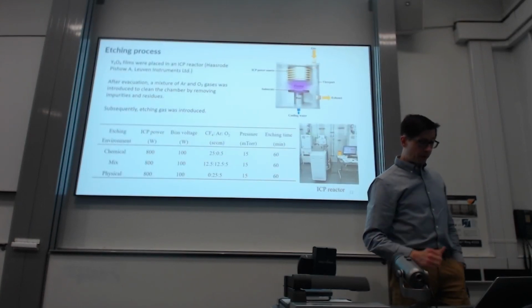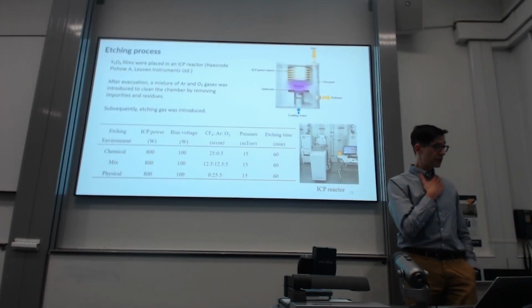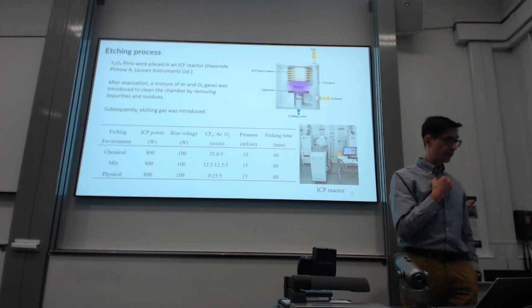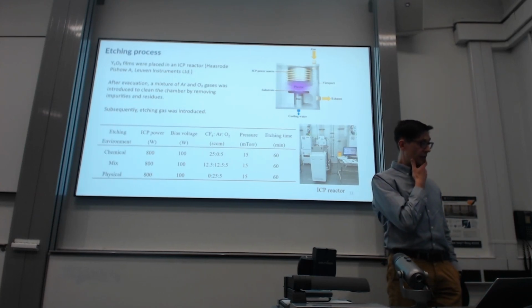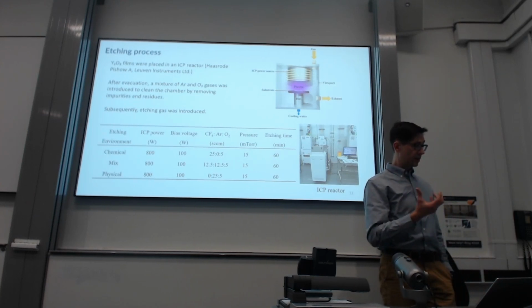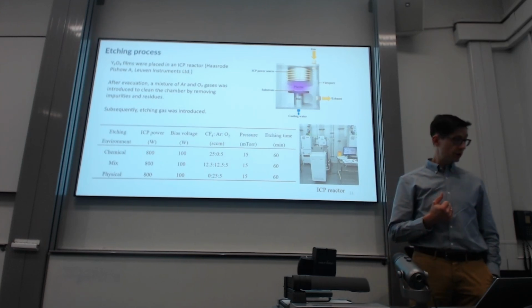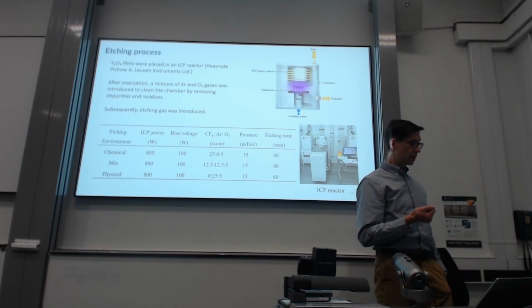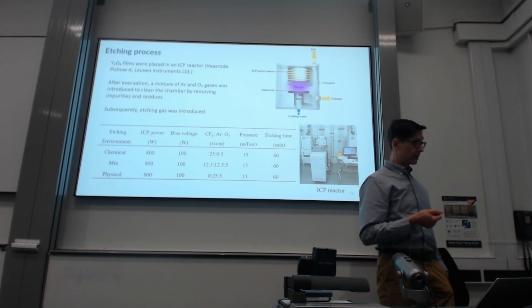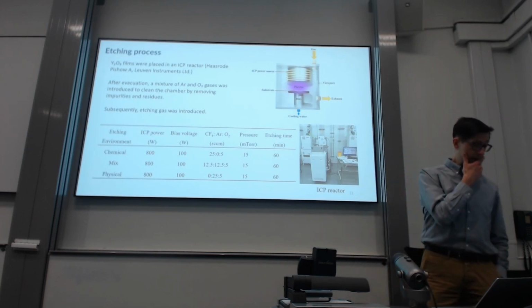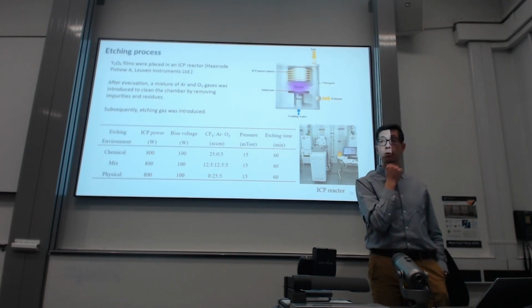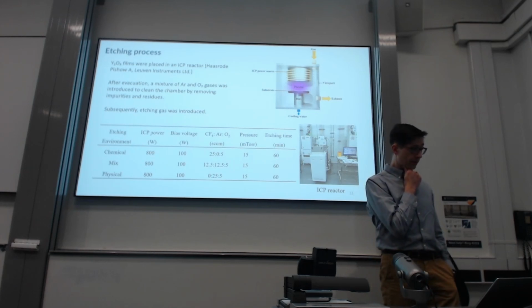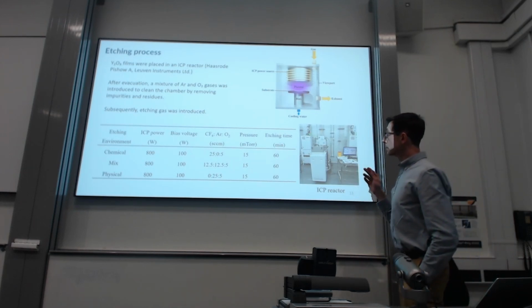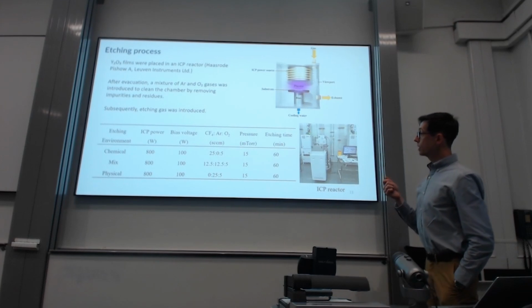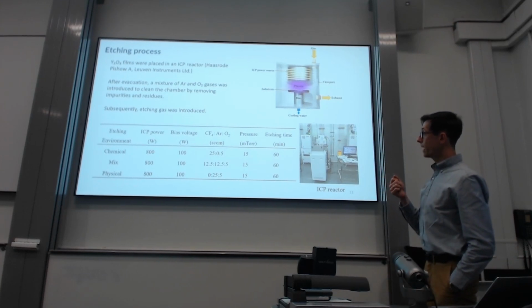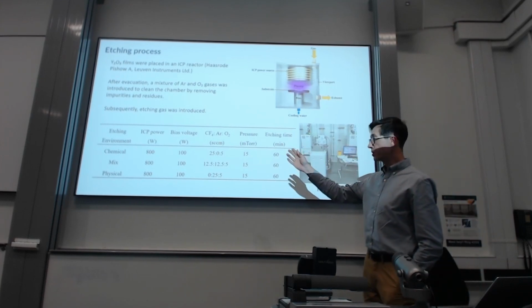So moving on to the etching process, which was done in an ICP reactor. After creating a vacuum, a mixture of argon and oxygen was introduced into the chamber, and then subsequently the fluorine gas was introduced for the etching purposes. So our colleagues distinguish here between etching, which they call chemical etching, and physical etching.